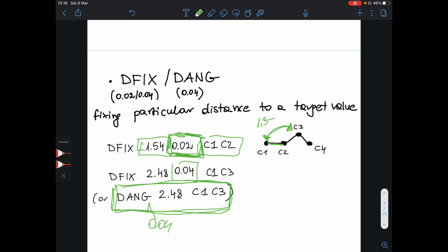And in general, when you deal with some easy disorder, you kind of have two options, right? You can either use same distance restraints to restrain these distances within one fragment to be similar to each other, or you could actually also use DFIX and just say that, well, we know that the carbon-carbon bond length when you have sp3 hybridization should be around 1.54, so we can also restrain all distances to be similar to 1.54 as a default value, right?